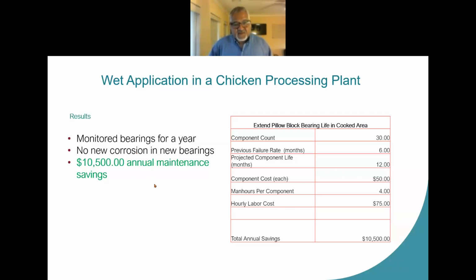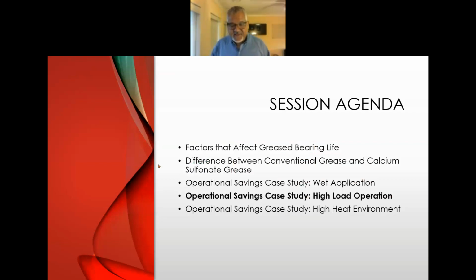And once they purged through all their bearings, they were using fresh bearings that lasted a heck of a lot longer. So we ran a cost savings calculation, say if 30 bearings in this cooked area, and the previous bearing failure rate is 6 months, then they projected component life. This is just a conservative estimate, since I only monitored them for a year. Say your bearings just doubled their life from what you've been experiencing. Say each bearing costs $50 for the material, and 4 man-hours per bearing at $75 labor costs, saves them $10,500 in annual maintenance costs. So here's the operational savings that the maintenance crew can brag about in their plant for this chicken processing plant cooked area. So that was a wet application case study.